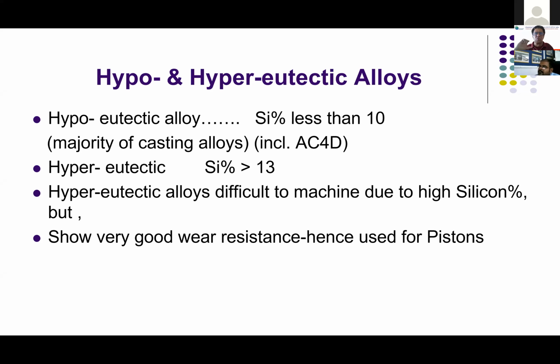The piston is the one which gets a lot of wear and tear, and therefore it requires extremely good high surface hardness. That is why we add more than 13% silicon. Hypereutectic alloy is very difficult to machine due to high silicon content, but shows a very good wear resistance, hence used in pistons.